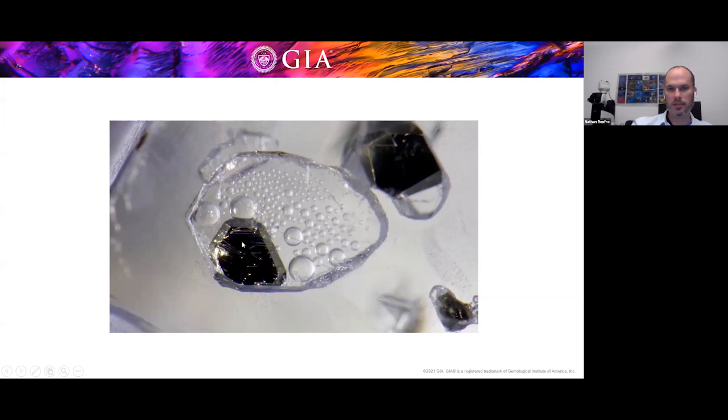And also, it's interesting that all of these negative crystals contain a graphite crystal. In a similar way to this unmixing, it appears that the graphite has unmixed from the carbon dioxide fluid, or that the carbon dioxide fluid had dissolved enough excess carbon to allow a graphite crystal to grow out of this solution upon cooling.